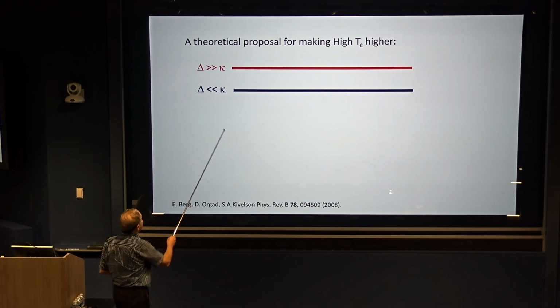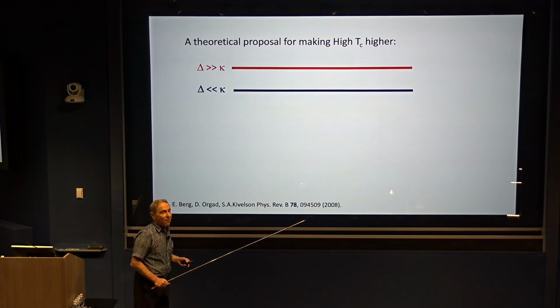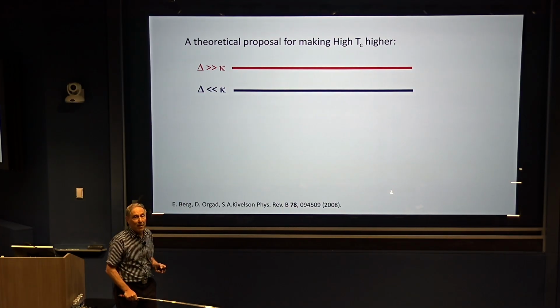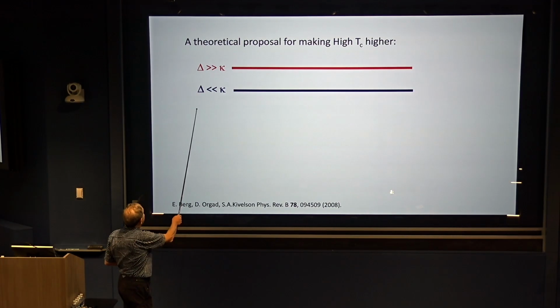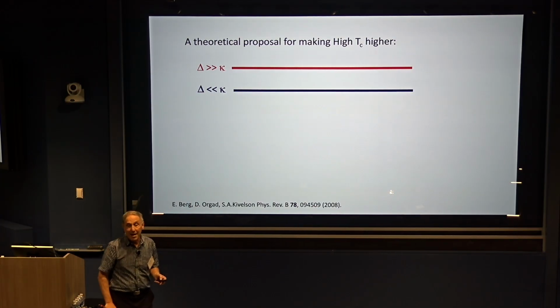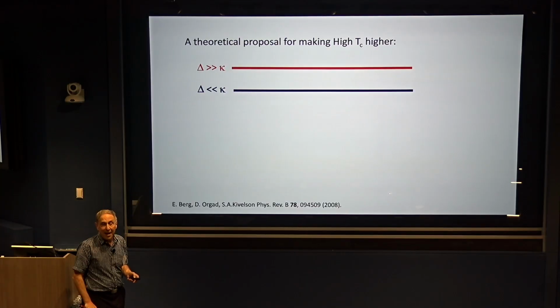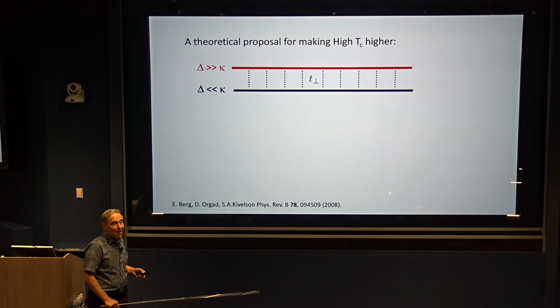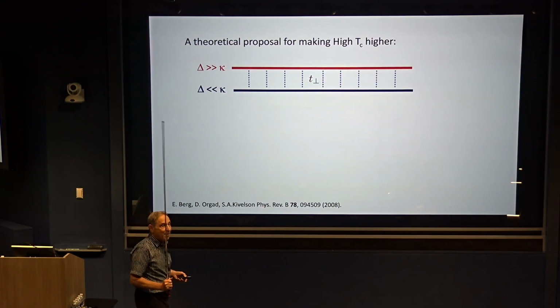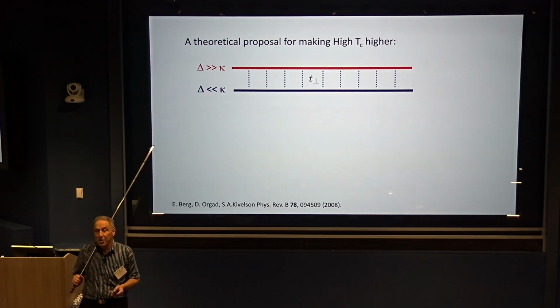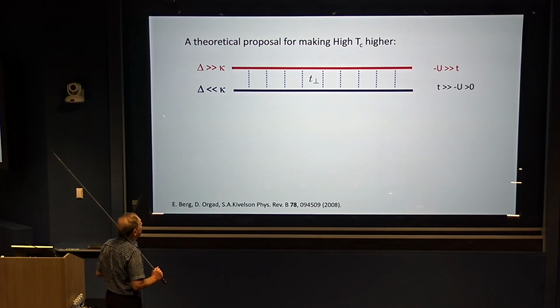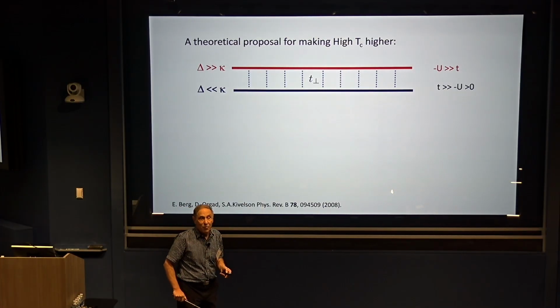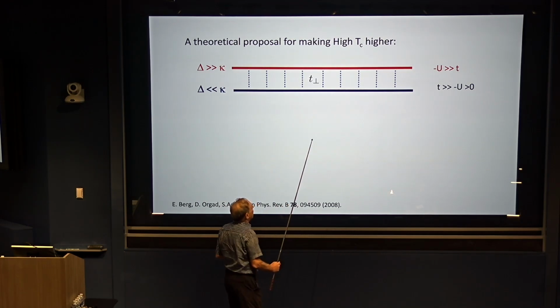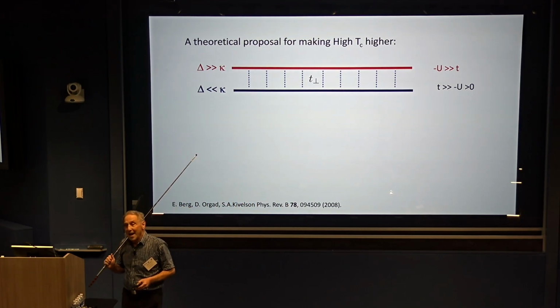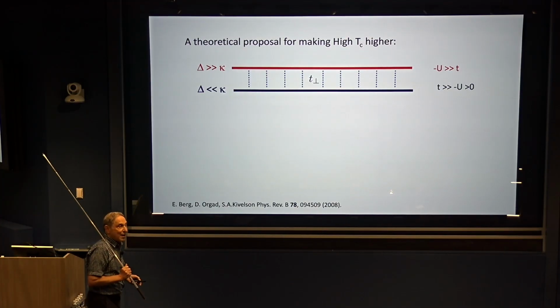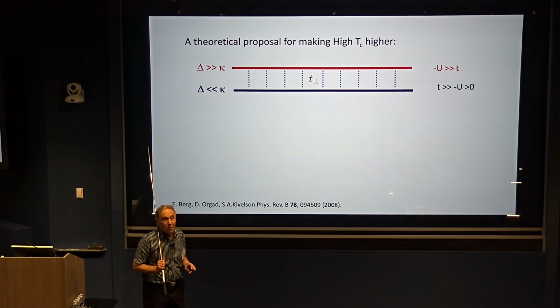calculations. We said, let's consider a model problem where we have one layer that has a big pairing scale but very low superfluid density. Let's have another layer that has a small pairing scale but a large superfluid density. And then let's turn on some weak tunneling between them, and let's see what we get in terms of superconductivity from this. And so to have a problem that seemed relatively simple, we took for the red layer to be a negative U Hubbard model with a really big negative U. So the superfluid density would be near 0.